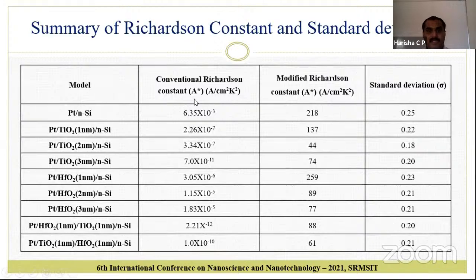There is also one more comparison. From the conventional Richardson plot and modified Richardson plot, we have calculated the Richardson constant. In the case of the conventional Richardson plot, the value of Richardson constant is very, very low. This is supposed to be 112 ampere per centimeter square Kelvin square for N-type silicon, but the conventional Richardson constant is very, very low. In the case of the modified Richardson constant from the plot, we have seen a very close value. And there is also a standard deviation with respect to the Schottky barrier height at various temperatures. This has clearly shown that there is an inhomogeneity in both the MS structure as well as MIS structure. The Schottky barrier height change may not be only because of the surface inhomogeneity. It could be because of some other reason which requires further investigation.